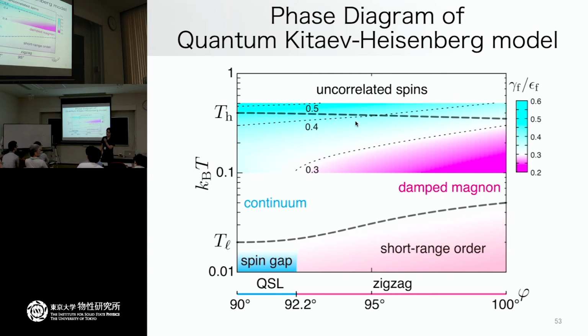Of course, if you're tuning a little bit, then for example, the high temperature scale for the S(q, omega) or heat capacity data can be fitted. But if you look at, for example, the gap size in the S(q, omega), then you need to introduce quite a large Kitaev coupling. For example, Takafumi-san already studied this point. And so far, no ab initio model can describe everything observed in the experiment.